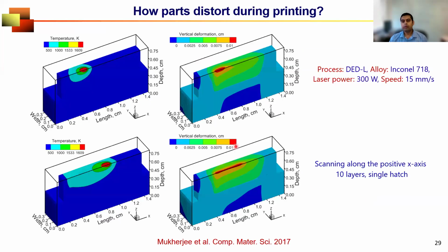So that type of modeling framework is enormously useful to provide scientific insights. For example, you see how the distortion or deformation field is evolving depending on the temperature. This is the temperature field, and this is the deformation field. You see, where the temperature is very high, the deformation is also high. Why? This is alpha delta T, high school physics. As the molten pool is progressing, this deformation field is also getting elongated. So this information is very useful to find out how much deformation you can get in the final part, and whether this is exceeding the allowable design limit.